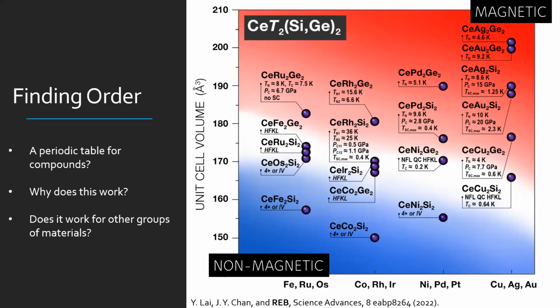So in one region of this phase diagram, up here, we find that if the unit cell volume is large and the D shell is more full, you get more of a magnetic ground state. If it's compressed and less full, you wind up with a non-magnetic ground state. And right at the interface is where you find these interesting examples that show superconductivity and so on. All right, so this is nice. It looks like it works well, but we want to start asking some questions. Why does it work? And does it work well for any other groups of materials? Or is this some sort of accident?